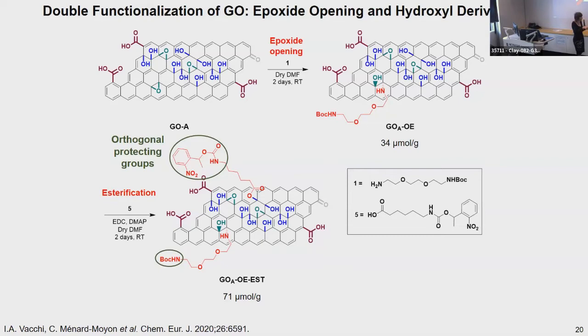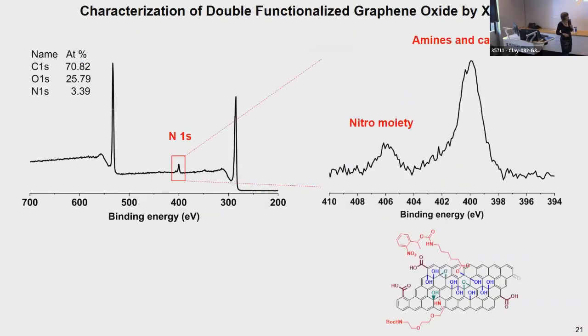in a sense that we can cleave one without affecting the other. And this photolabile protecting group is interesting because it has a nitro moiety that facilitated the characterization of the material and confirmed the occurrence of the reaction, in particular by XPS. This is the XPS survey of the double functionalized graphene oxide. And looking at the N1s peak here, there were two main peaks. This one at around 400 electron volts, assigned to the amines and carbamates. And most importantly, this one assigned to the nitro moiety, confirming the presence of this nitro group on the surface of graphene oxide, and so confirming the outcome of the reaction.